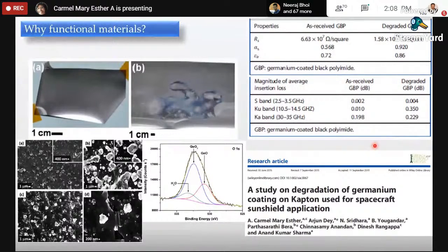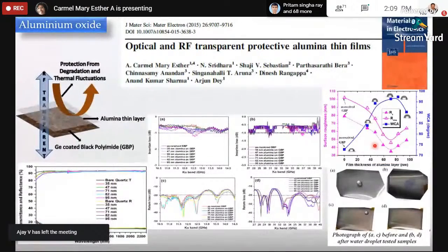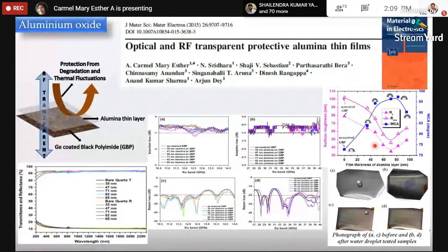So this is the major work which I did at the Indian Space Research Organization as my doctoral fellowship. It looked like a very simple problem, but it's a functional material. So when we tried to solve it, we faced many issues, and finally we optimized it and got the solution. What we did was tune a thin aluminum oxide layer over the germanium black polymer, and we studied the effect of this layer as a function of thickness, with several environmental studies. So this is the evidence.